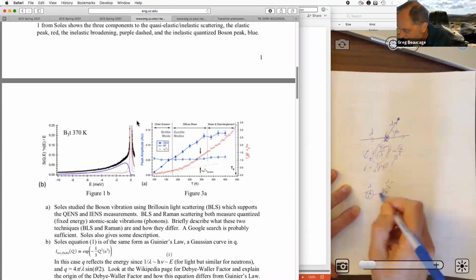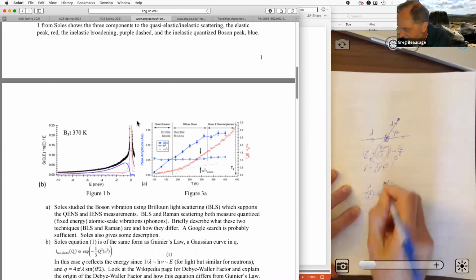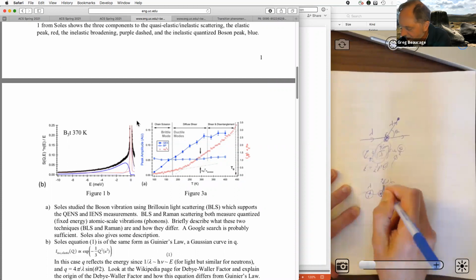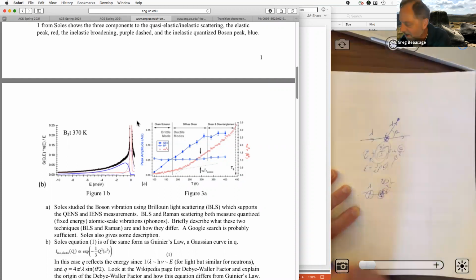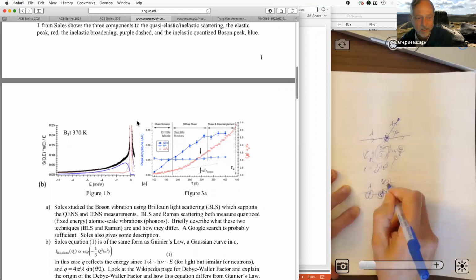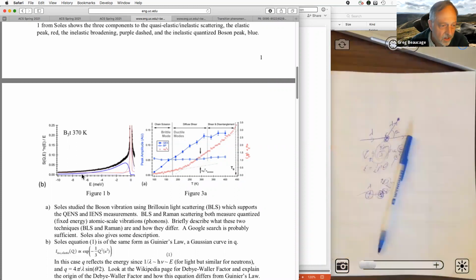But if there's an energy loss that goes on here, this wavelength can drop or increase depending on what kind of energy loss happened. Right. So that means your wavelength would change. So that means if you plot out the intensity versus the energy, which is related to the wavelength, then you'll see that this thing goes from a sharp peak, like monochromatic, and then broadens out. And there are two kinds of broadenings that happen. One is just the Debye-Waller broadening, so the peak just gets broader, and the other kind is quantized, it's at a fixed energy value.